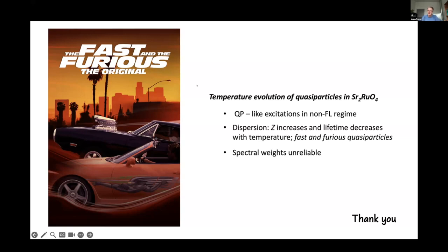Yes, that's exactly what I wanted to say. So DMFT or mean field theory finds that correlation becomes smaller, and I illustrate this by saying Z increases, so that it goes to nearly 1. The analysis of the experiment seems to support this. So the mass enhancement becomes smaller, which is consistent with Z increasing. So yes, that's exactly what I wanted to say.